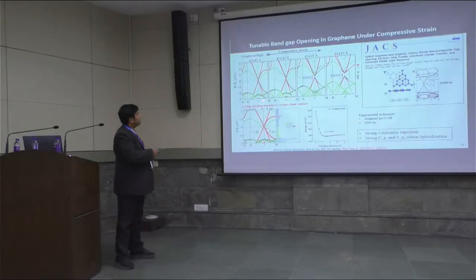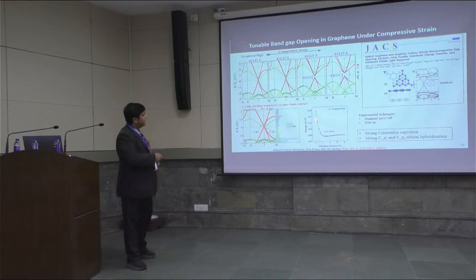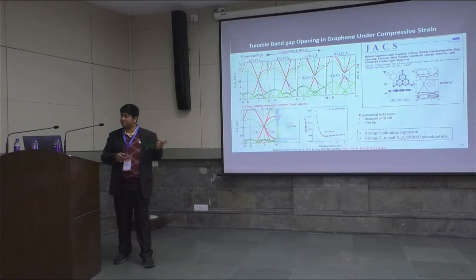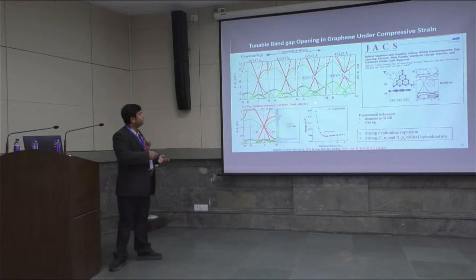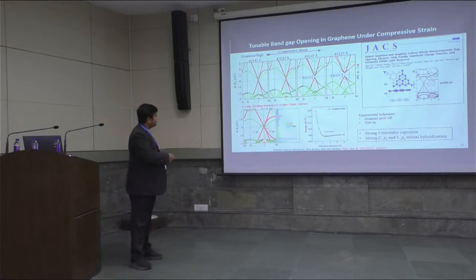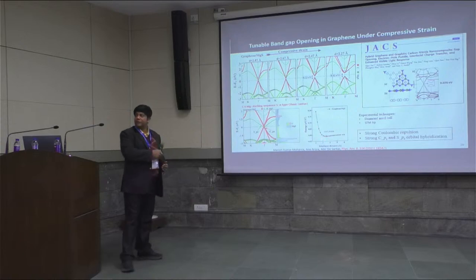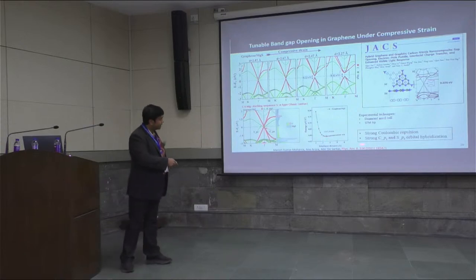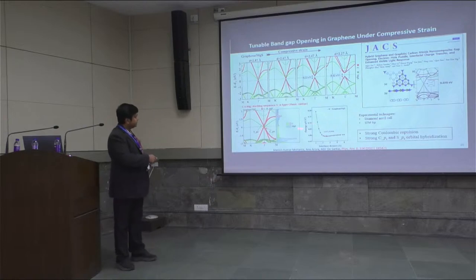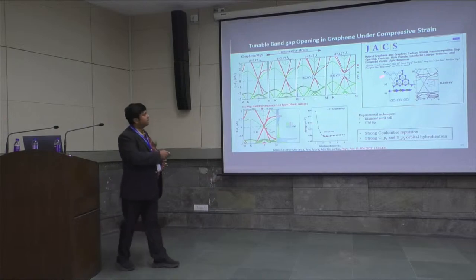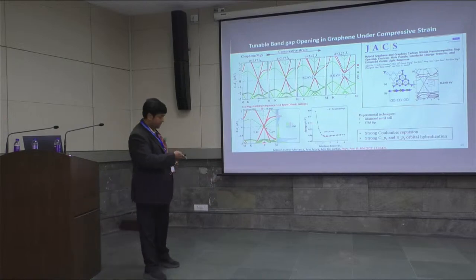And then we have also opened the band gap in graphene by the application of vertical compressive strain. This has relevance to Professor Pandey's talk in the morning. When the two layers are brought closer to one another, there is a strong hybridization of the sp2 and pz orbitals. And when you go past the equilibrium distance of separation, there is a strong Coulomb repulsion. A cumulative effect of these two factors facilitates the opening of the band gap. The band gap which is opened is much higher than the ones reported earlier.